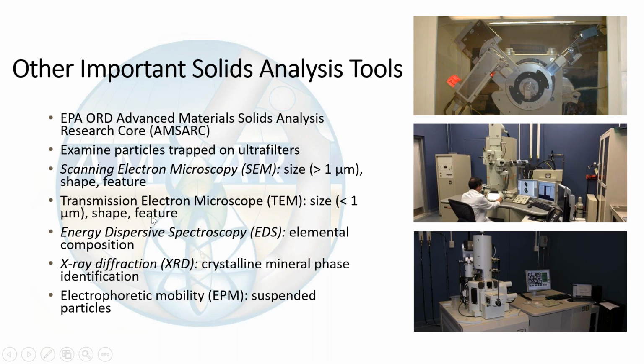and can tell you something about the elemental composition, and it has electron diffraction, so it can tell you something about the crystalline nature, if the particles are crystalline, and help you identify what they are. EDS, again, I mentioned that, can be connected to or part of the SEM and the TEM, or used as a standalone approach. X-ray diffraction tells you about the crystalline nature of the particles, and can also help you look at crystallite size. And of course, if the particles are in suspension, you can use an electrophoretic mobility measurement to give you information about the charge and sizing of the particles as well.